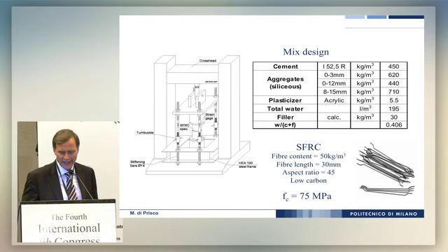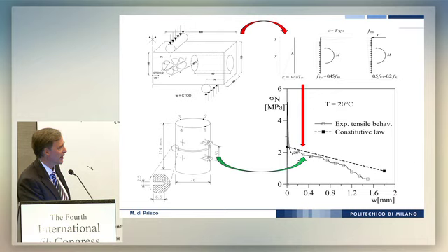We can also check the behavior of the constitutive model we suggested, so for instance, a linear behavior. And we did coring directly in the three-point bending test, or in this case, the four-point bending test, a cylinder. And so you can arrive by means of this model to a certain linear branch. And after, by coring, you can test the uniaxial tension and fixed end specimen, and you see that the difference is not so important. And we did it for a lot of cases, and this works.